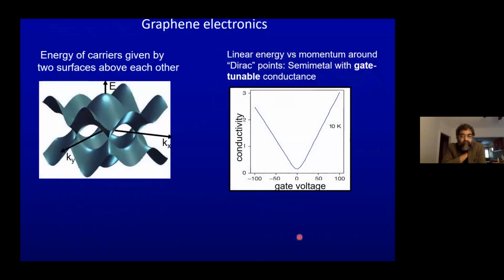Now, we care about the electronic properties of graphene, so I'll say a little bit more about that. This is the famous band structure calculation on the left here by Wallace that was done in the 40s, I believe, in 1947, and then was basically kind of ignored for 60, 70 years until now. It's one of the best cited papers ever after graphene was experimentally discovered in isolated form. He showed that the energy of the carriers in graphene is given by two surfaces above each other, as you can see here. And then these surfaces touch at single points. This is the Dirac point of graphene. So what does this mean in terms of measuring conductance? It means that if you measure conductivity versus gate voltage, you get this linear energy versus momentum around these Dirac points.